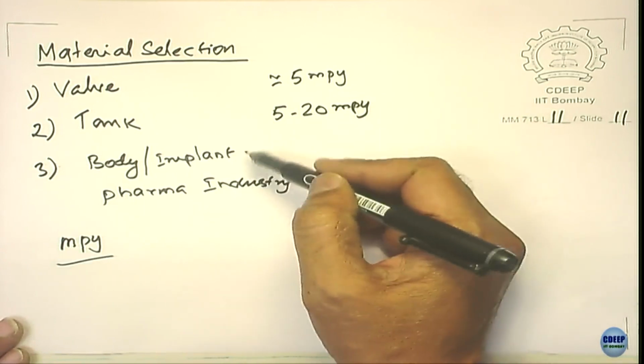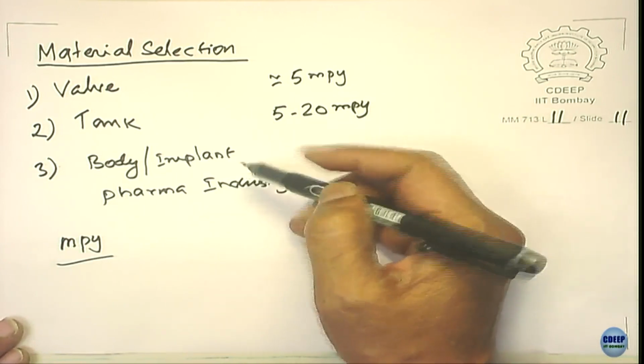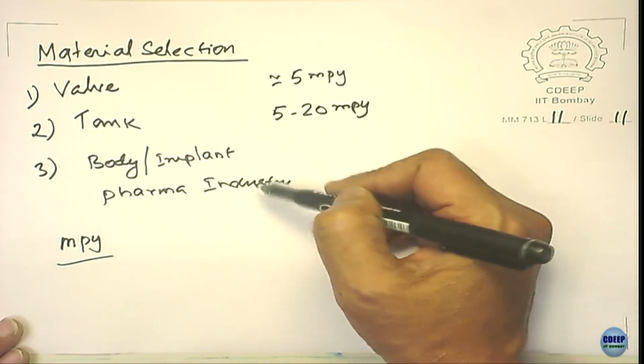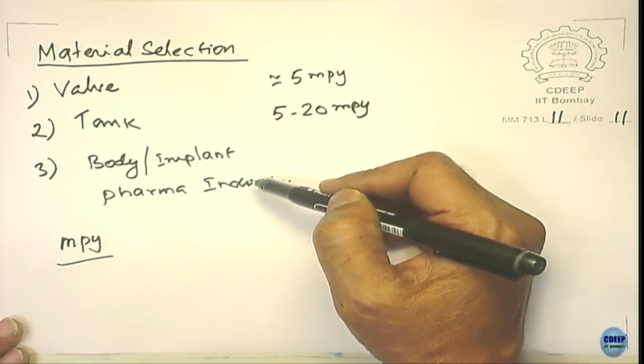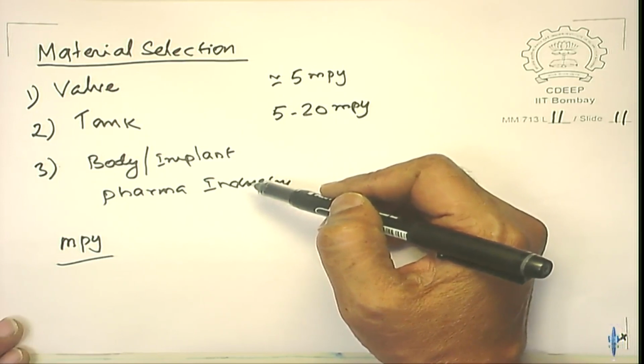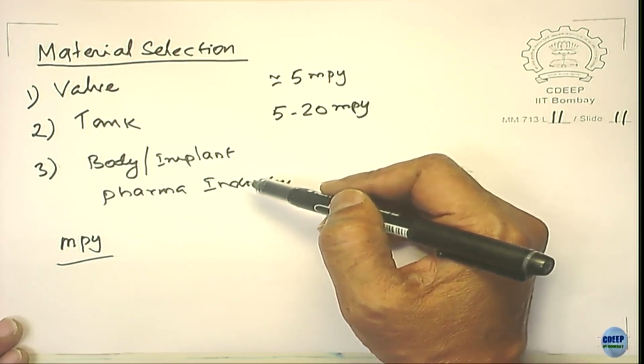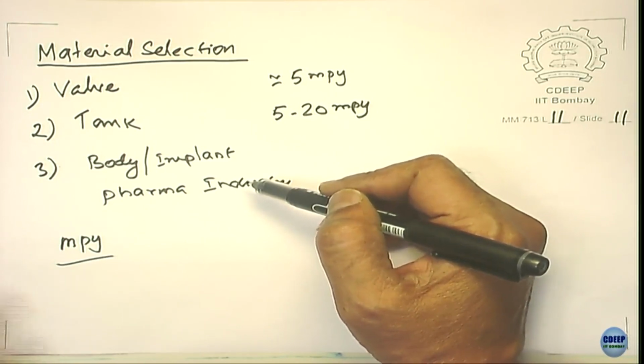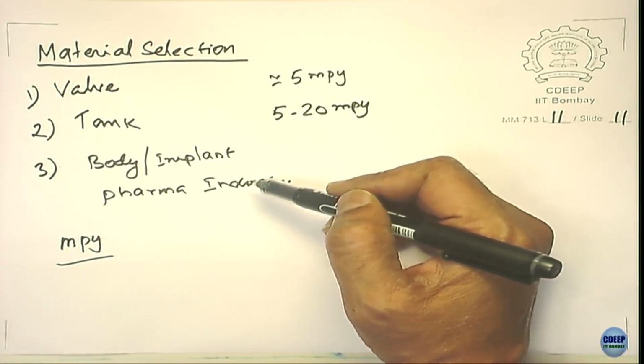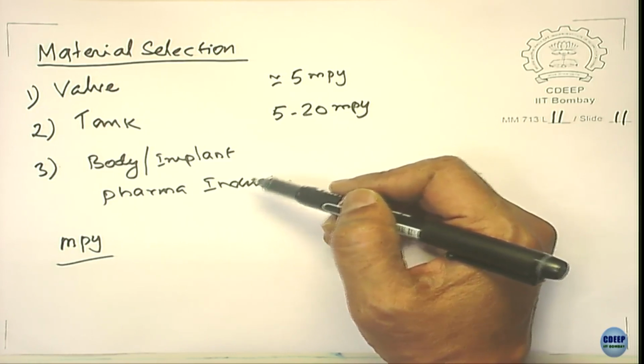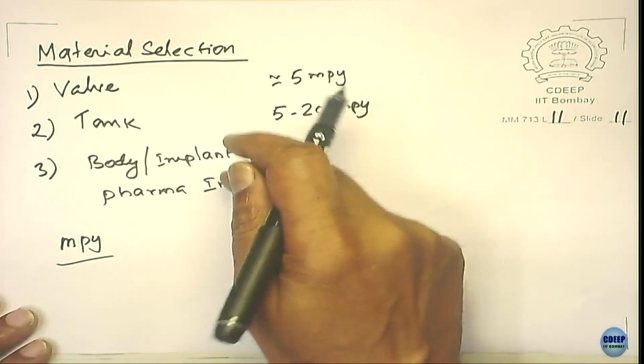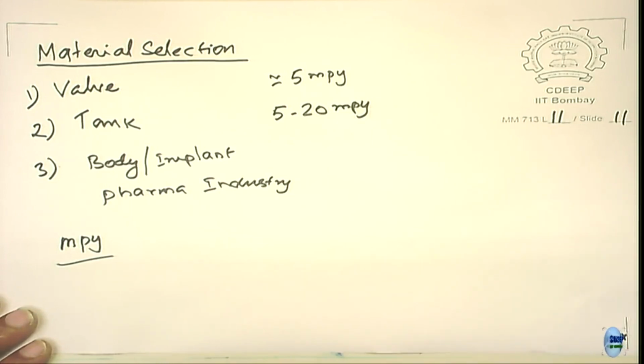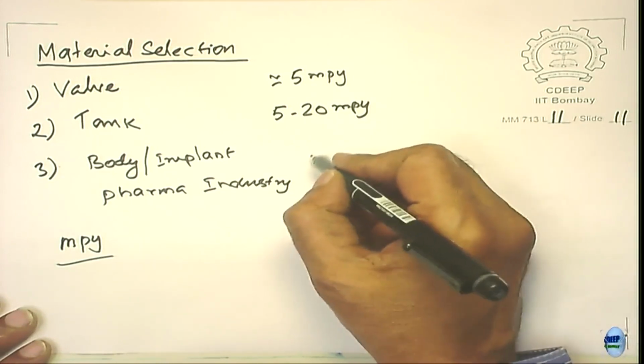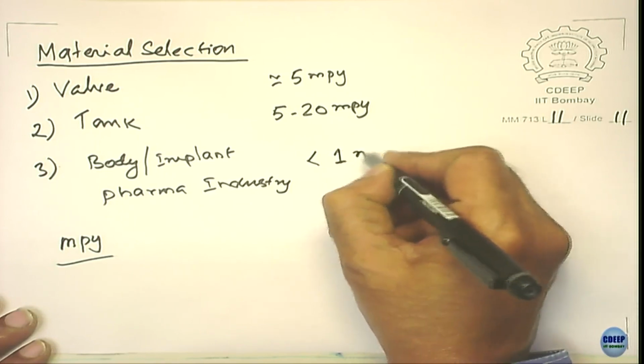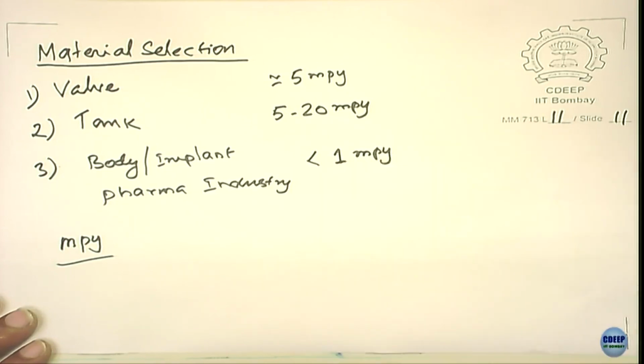And here the problem is not structural integrity, the problem here is more of tolerance, right. The body will not tolerate a bit of nickel ions getting segregated due to corrosion. You may have an implant mechanically stronger, no problem. So, here the corrosion rate is because of the contamination issues. So, here the corrosion rate has to be lower than 1 MPY.